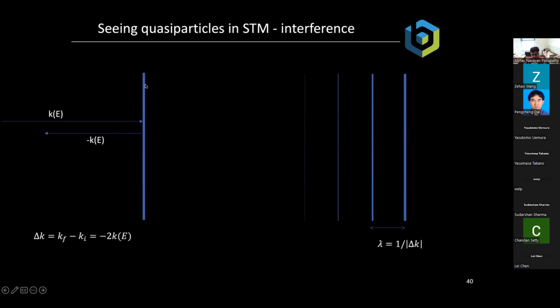So how does this interference work? If I have a step edge in copper and I have an electron with momentum k at a given energy E, it bounces off the step. And if it bounces elastically, it goes back with momentum minus k at the same energy. And this incoming and outgoing wave are going to interfere with each other generically. And the momentum transfer in this is kf minus ki, which is twice k in this particular case. So what this means is I'll see an interference pattern near the edge of the step. And the wavelength of this interference pattern, lambda, is proportional to 1 over this delta k. So by measuring the wavelength of these interference patterns, I can tell what the momentum of the electron was at that particular energy. Now, this is a special case of a step edge.